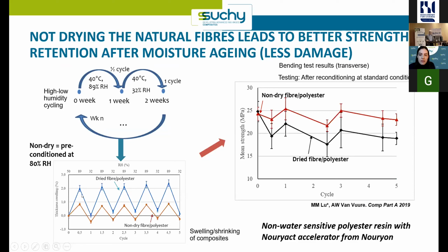And also you see here for the mechanical properties that in the red is the non-dried fiber, that we maintain much better strength. And this is in transverse direction, so really loading also the interface and the transverse side of the fibers. We keep much better properties over time, you see here the amount of cycles, than for the case where we had fully dried the fibers. So this idea really seemed to work.